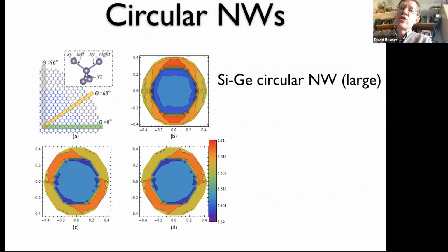So this now shows silicon germanium core shell nanowires. So you've got a silicon core there on those diagrams. That's the sort of dark blue, and you've got a germanium shell. And actually, the three highly colored diagrams are showing you the strain in those nanowires projected onto different directions. So the blue shows that the silicon is being expanded, and the red and the yellow shows that the germanium is being compressed. So we can understand where the strain is laid out.